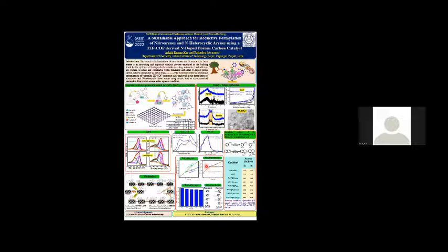Further, we tested the hot filtration test. What does the hot filtration test mean? During the reaction, at a certain time, we remove the catalyst and let the reaction run for its original time, and we can see here that there is no improvement in the reaction. That means the reaction is only catalyzed in the presence of the catalyst. So keeping all these things in mind, we deduced a mechanism where this is the active center. This is the graphical presentation.